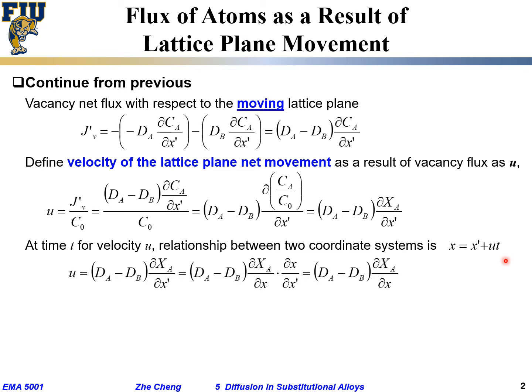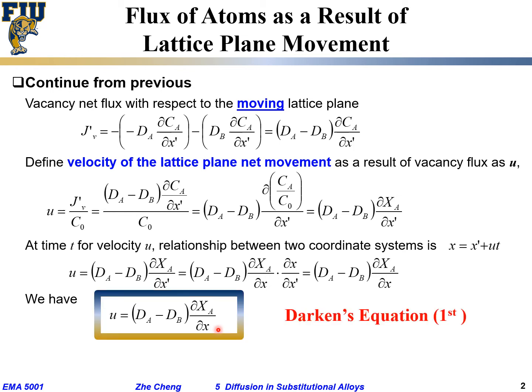Make sense? So as a result, do you see that this velocity would be just dA minus dB times partial of the molar fraction of A with respect to x prime, when we are doing this manipulation. X prime is still here, but partial x is in the numerator, right? I just put it here. And what is the partial x with respect to partial x prime from here? It's 1, right? The partial differential of x with respect to x prime is just 1. As a result, that's our velocity, moving velocity. We would have u for the velocity of my chosen lattice plane, or my reference point. It's moving at this speed. Okay? This is our so-called Darken's equation, the first Darken's equation.